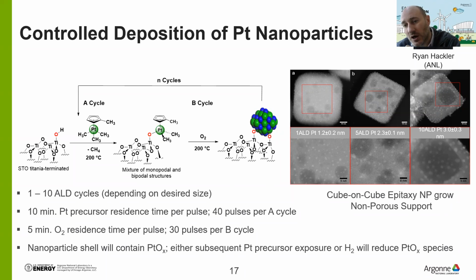We also show, of course, that platinum ALD is not a scalable technique to make platinum nanoparticles, or nanoparticles in general. And we show that we can also use classic solution-phase platinum nanoparticle deposition to make these particles, these catalysts, sorry.